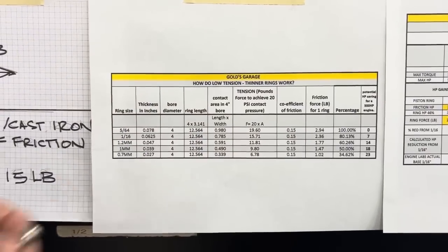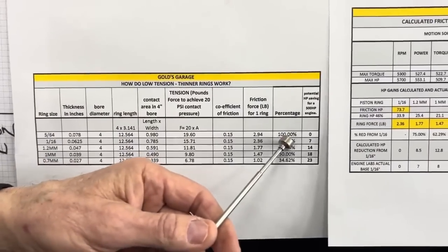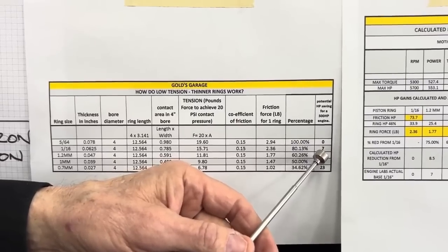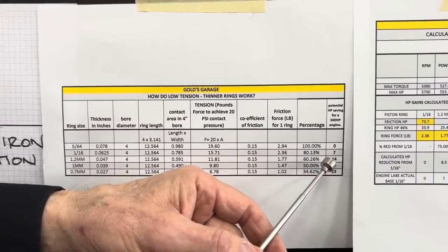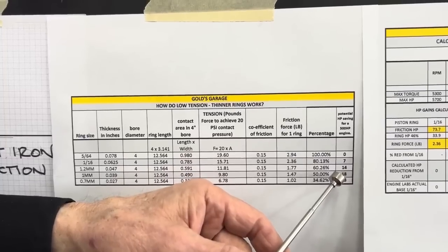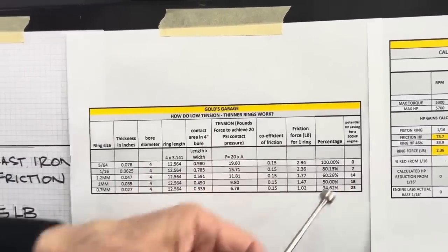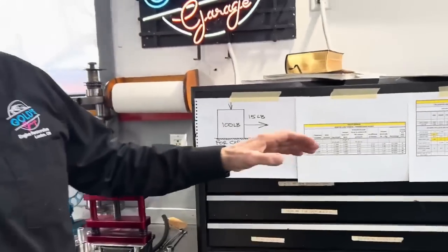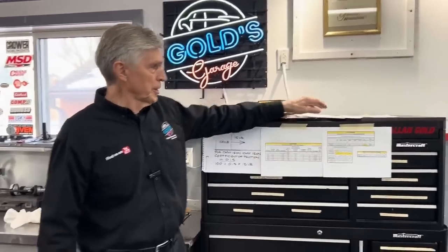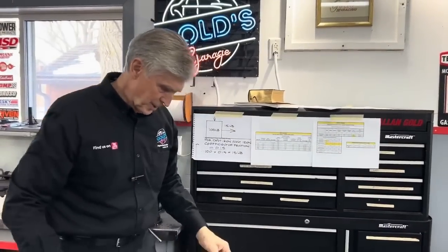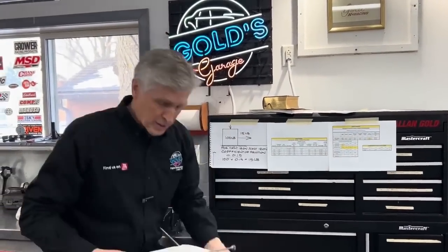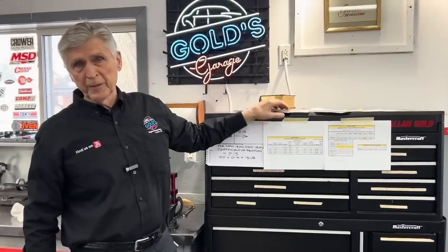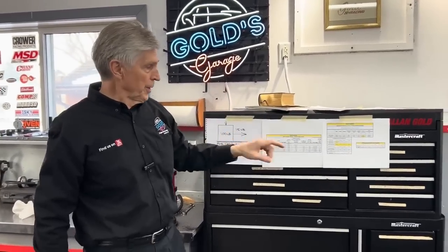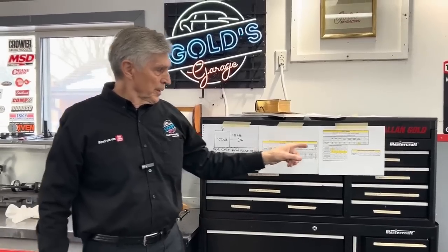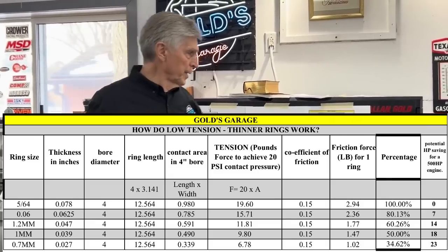So here's my calculation. Obviously the base case is 5/64. A 1/16 ring, you'll gain 7 horsepower, 1.2 millimeter, 14 horsepower, 1 millimeter, 18 horsepower, and a 0.7 ring, 23 horsepower. That calculation is, once again, RPM dependent. So using Mike's engine for reference, it peaked horsepower at 5,700 RPM. So those numbers are calculated based on that. Keep those numbers in mind because we're going to come back to them in the calculation.